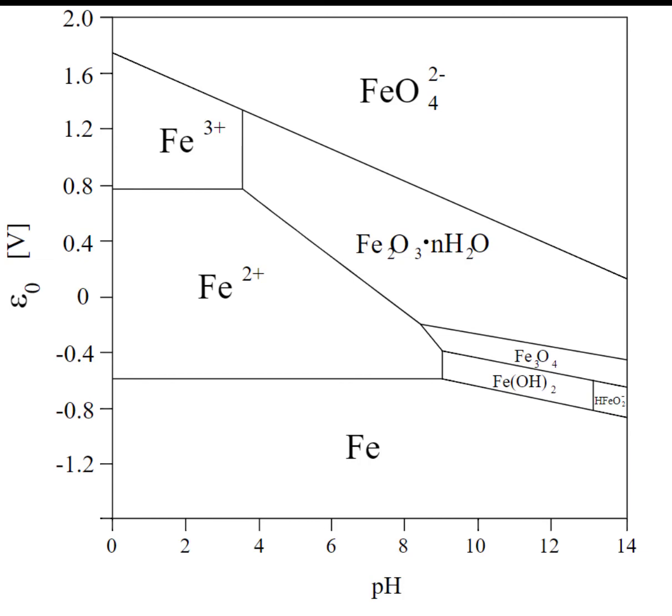Just at this pH, iron 2 oxide is soluble, completely soluble. Iron 3 oxide forms a solid. So we end up stuck here. And then we will build up an iron oxide layer and suddenly the reaction will stop.